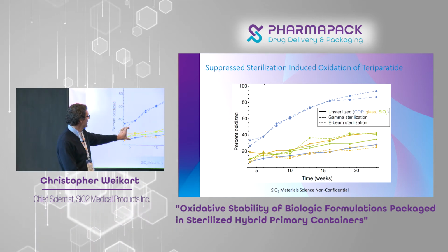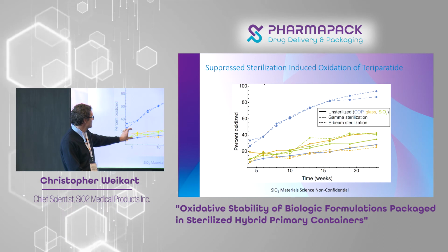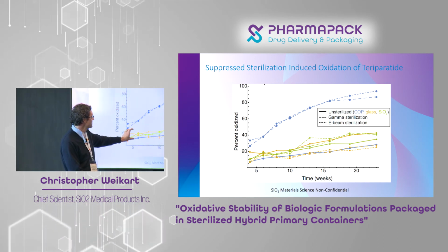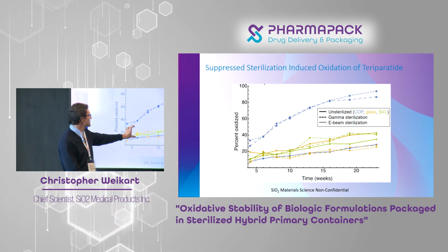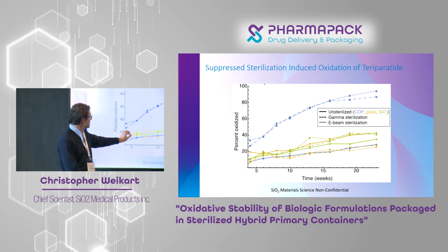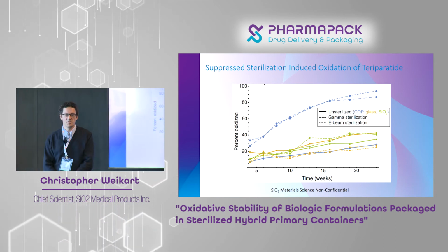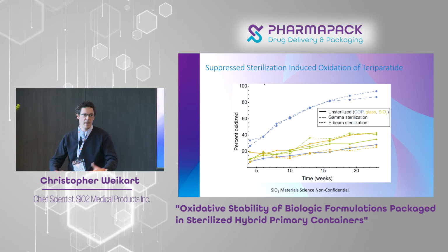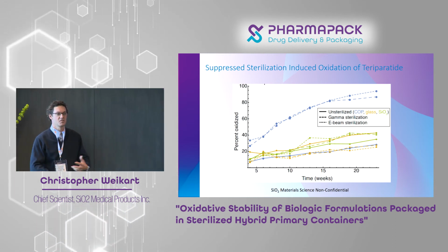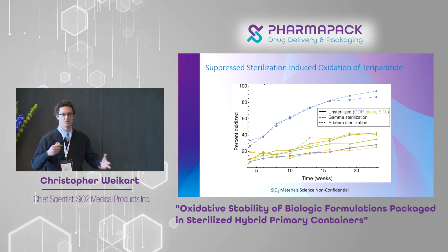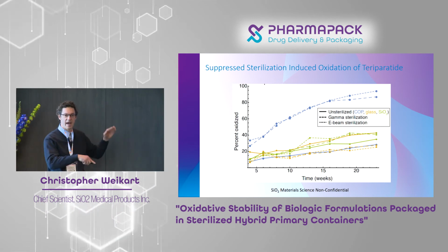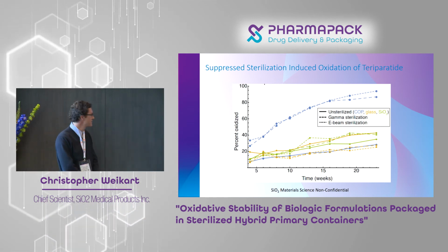And then in this range, you're seeing obviously the gamma sterilized glass in our container, and then an unsterilized COP. So you can see a little bit of chatter there. Of course, you can imagine when you're sterilizing a large batch of containers, there's certainly variations in dose throughout the batch. We attribute some of that variation to things of that nature.